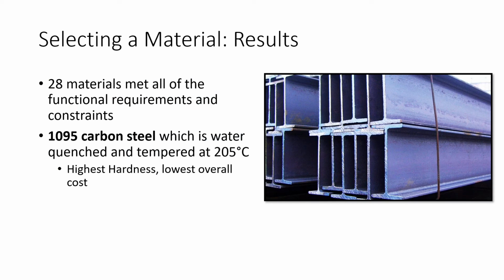28 materials met all of the functional requirements and constraints. Cast iron did have the cheapest raw material cost, but was deemed overall more expensive than carbon steel due to the machining process which would be required. This made the 1095 carbon steels the least expensive. 1095 carbon steel, which was water quenched and tempered at 205 degrees Celsius, was selected since it had the highest hardness, which would extend the rail's lifetime by reducing wear. This material also used water for quenching and was tempered at the lowest temperature, further reducing manufacturing costs compared to other options.